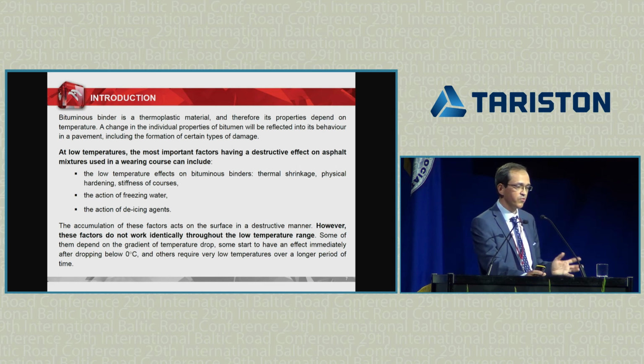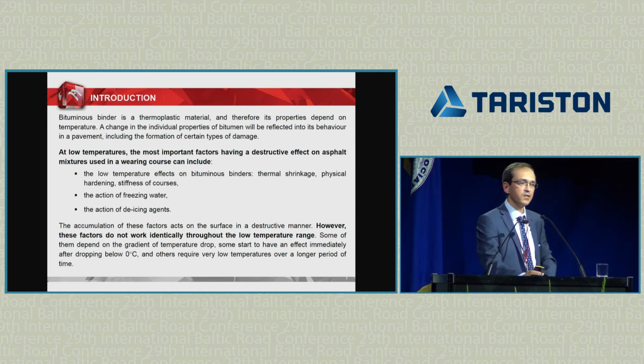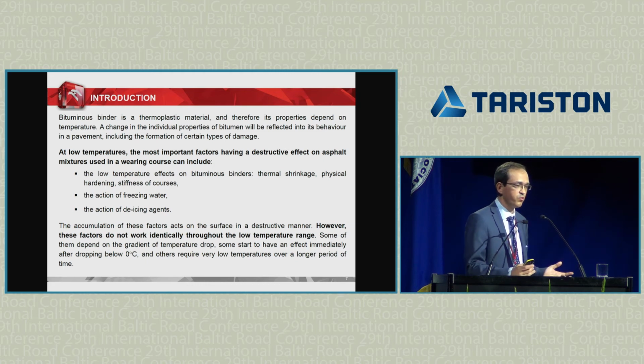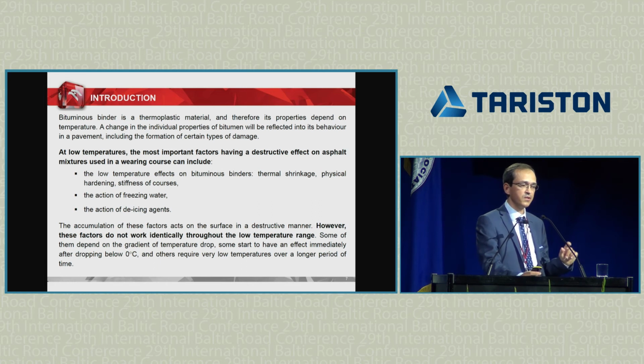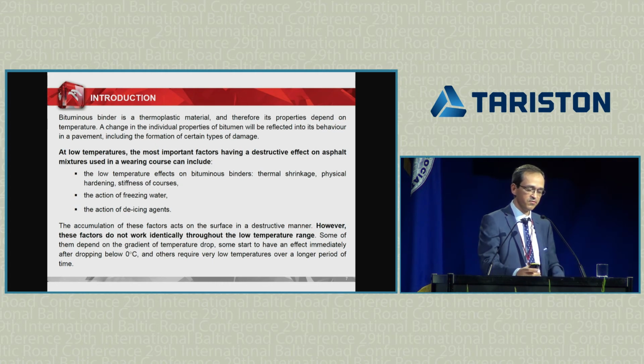We know that usually there is not only one factor, but at winter time we have, let's say, the sum of all factors. And what is important, those factors don't work identically throughout the low temperature range. We know that the asphalt mixture behaves in a different way close to zero when the water is freezing, in a different way in a very fast drop of temperature, and in another way if the low temperature lasts during a very long period.